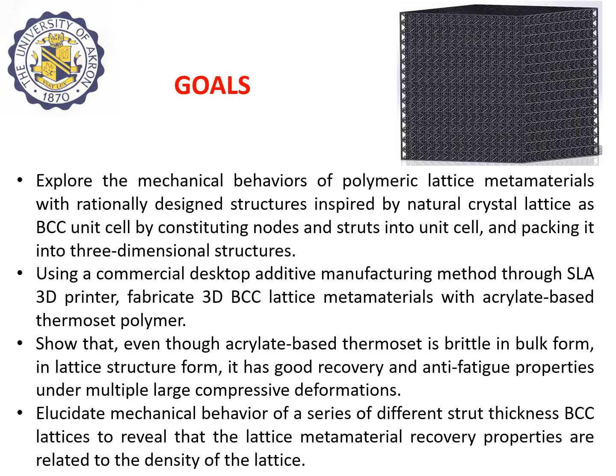Using a commercial desktop additive manufacturing method through SLA, we fabricated 3D BCC lattice metamaterials with acrylate-based thermoset polymer. We wanted to show that even though acrylate-based thermoset is brittle in bulk form, in lattice structure form it has good recovery and anti-fatigue properties under multiple large compressive deformations.